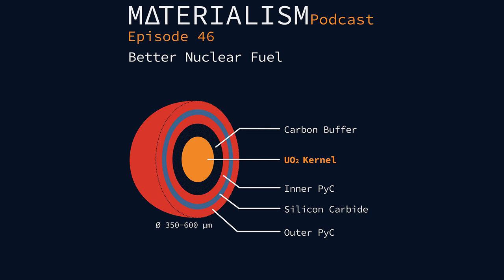Makes sense. But even then, a lack of particle strength and the inability to retain any heavy fission products like cerium or strontium or cesium led interest to refractory coatings for particles, and silicon carbide is the obvious choice because of the inability for many atoms to diffuse through it, its high temperature performance, and its high strength, and it's also pretty well understood as a material. We've used it for a lot of things, right? It's an abrasive. We know how to make it with powder metallurgy because it's a tiny particle, right? We make it all the time.